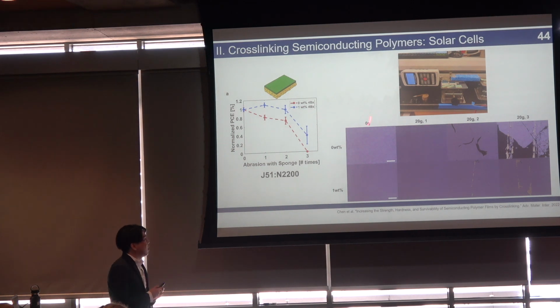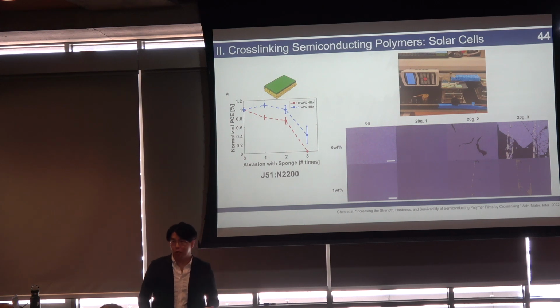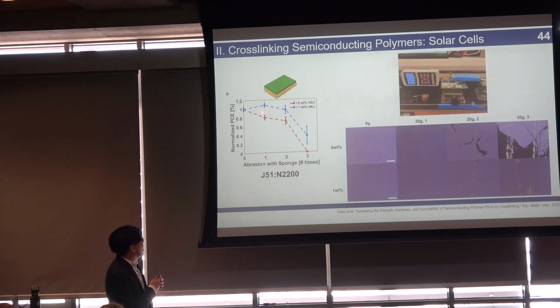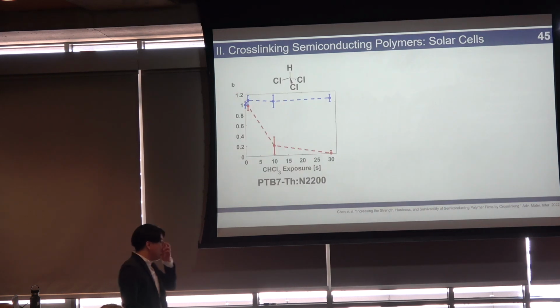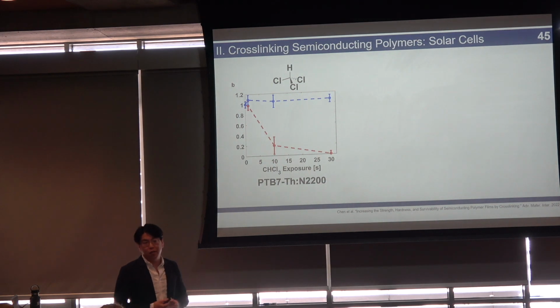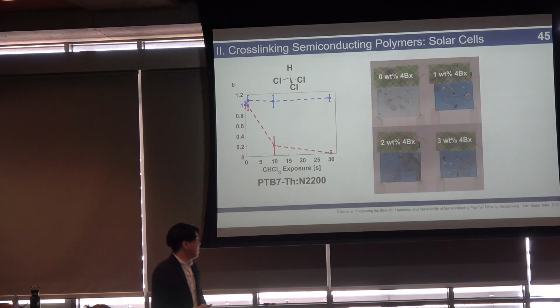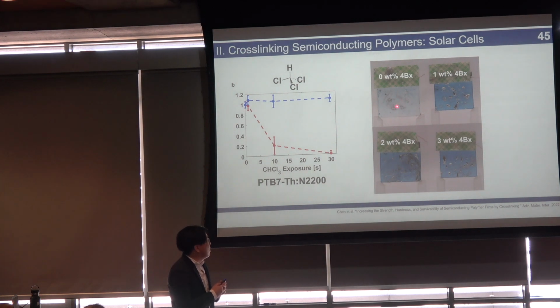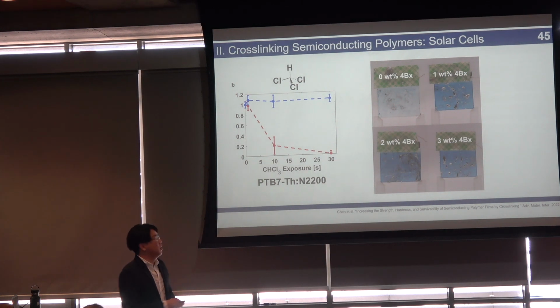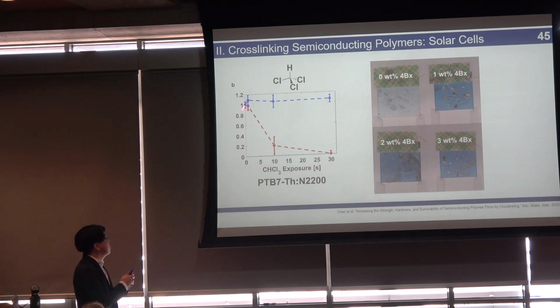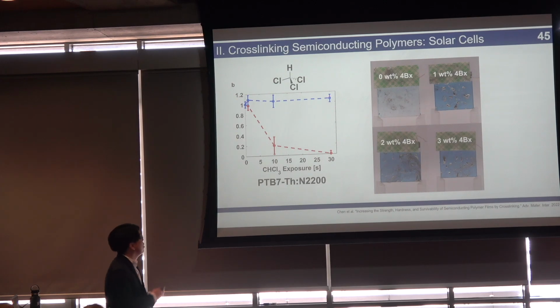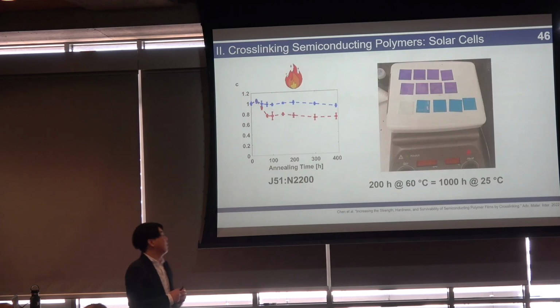For example, we can create this sort of janky setup where we drag a sponge over the solar cell, and we see that the cross-linked film survives a lot longer than your non-cross-linked film. We can also make use of the insolubility of your bulk heterojunction. For example, we could throw these in a vat of chloroform, which is a very strong solvent, and we see that the non-cross-linked material washes away, and the cross-linked ones don't. So, of course, your cross-linked solar cells remain stable, your non-cross-linked ones dissolve and are inactive.